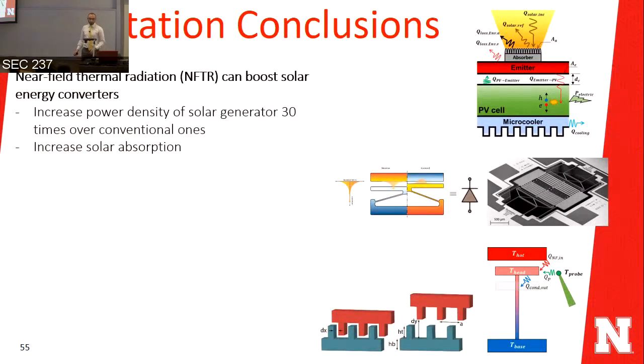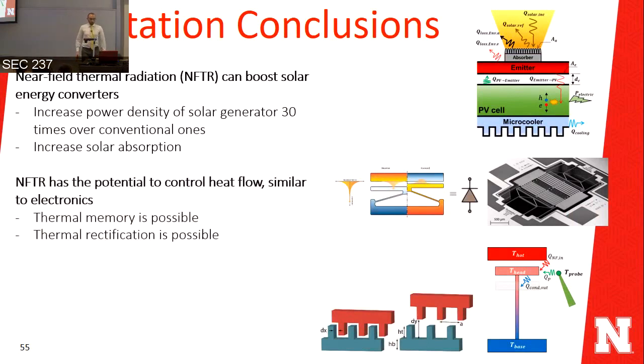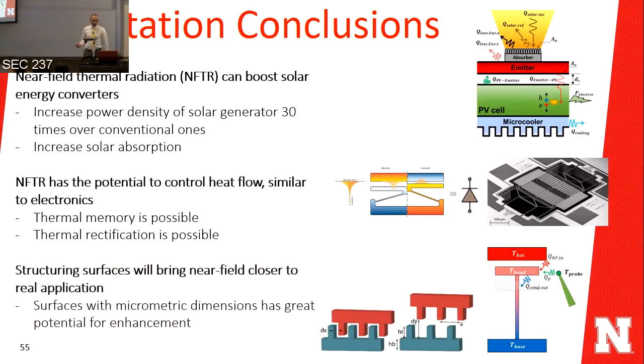So what you can get out of this presentation is that near field thermal radiation can achieve 30 times higher energy density than normal solar cells. You can increase the solar absorption by applying near field to solar thermophotovoltaics. Thermal memory and thermal diodes are possible with near field thermal radiation. We have proven this experimentally. And structured surfaces can bring near field thermal radiation closer to practical applications.